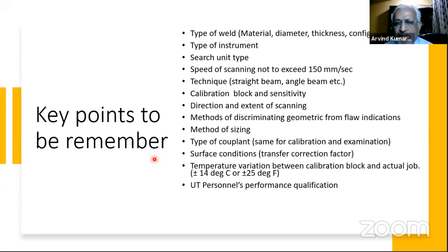What is that? Temperature variation between the calibration block and the scanning surfaces should not be more than plus or minus 14 degrees centigrade. Now you see, calibration is generally done in an AC room where the temperature could be maybe 20, 24, somewhere around that. And testing in, say, summer is done outside where the temperature could be 30, 35, or even 40. So the difference goes much beyond what is permitted by the code. It could result in variations and errors in your system, so you should be very, very careful.